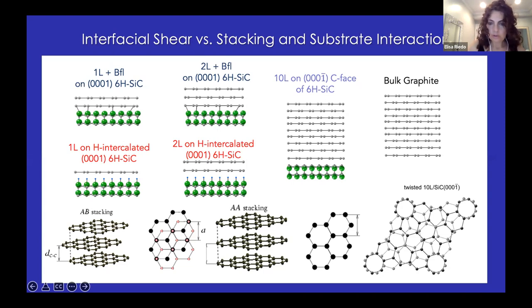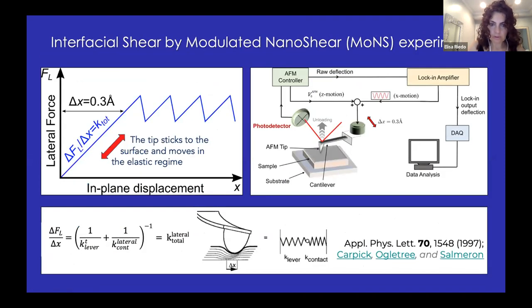Okay, so what have we found? Well, first of all, this is an overview of the methodology. It is very similar to the modulated angstrom indentation I showed before, except that now we shear laterally. And essentially what we do, we move in this area where, you know, this is the classical lateral force versus displacement that we have seen many times in this conference, right?